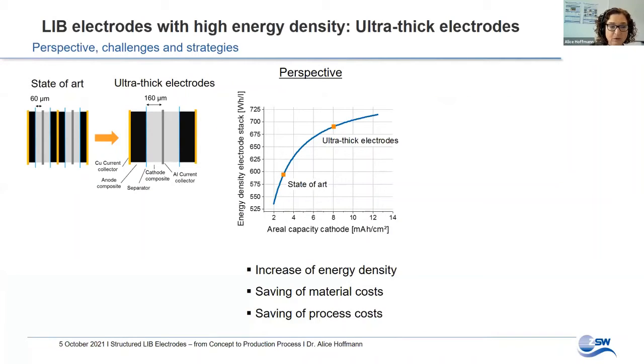Within the next years, a huge increase of global demand for lithium ion batteries is expected, which will be dominated by high energy applications. One approach to implement high energy density on electrode level is to make the composites ultra thick. In common lithium ion batteries, the electrochemical active composites have a thickness of roughly 60 micrometers, and a considerable share of the electrode stack consists of passive material like current collectors or separators. By laying out the composites ultra thick, the share of active material increases, and so does energy density.